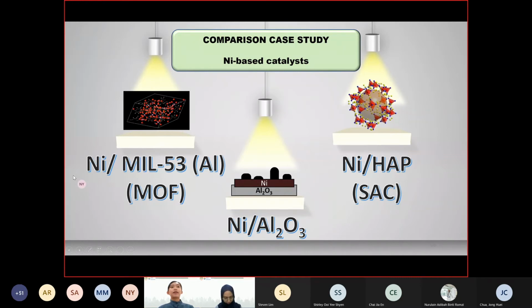The research group has carried out a comparison case study between nickel-based catalysts. To prove the feasibility of the novel catalyst in the dry methane reforming process, the research group has benchmarked the performance of nickel-based MOF catalyst, single-atom catalyst, and the conventional catalyst, which is on alumina. The MOF-based catalyst is nickel-supported on MIL53, whereas the single-atom catalyst is nickel-supported on HAP. Now, I will pass the floor to my teammate, Jialing.